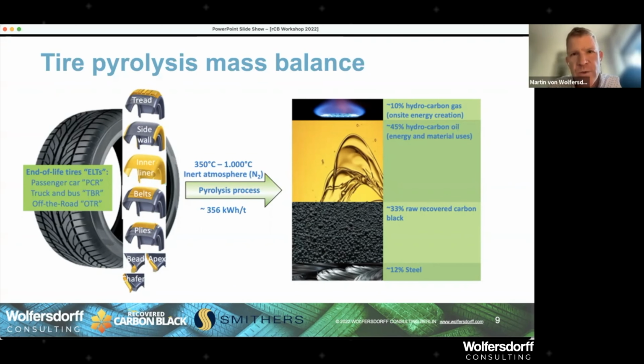So you would choose truck and bus tires or OTR tires, which have a very similar composition as truck tires. For example, mining tires, you know, the big oversized 4-ton tires, up to 3-4 meter big tires. They are really, really nice raw material for the pyrolysis, high natural rubber content, and very narrow content of carbon blacks. We get to that in a moment. So truck tires, mining tires, high biogenic content for the oil. And then, of course, the value creation for all products, the oil and the recovered carbon black is high.